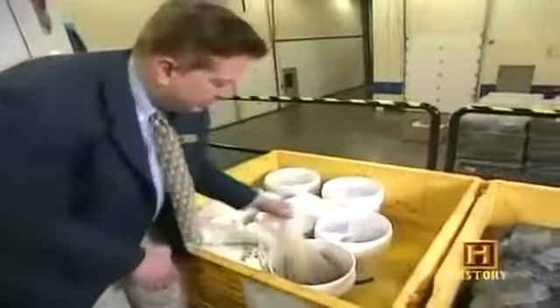We've taken the materials that we just described, and we're actually going to use a technique called upside-down mixing, where we're going to load the carbon black, the balance of the fillers and plasticizer, and then load the polymer, the raw synthetic EPDM, last. Lower the ram, masticate, put this together, and then based on temperature, we will add the curative to the mix to get a homogeneous mix.